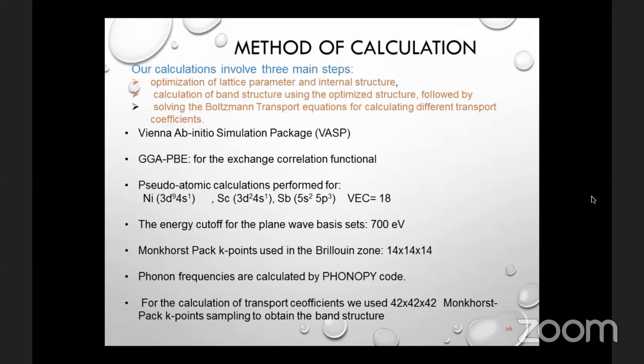But for the band structure calculation, we need more detailed and more sensitive band structure. So we increase the k-point mesh grid, because for the calculation of transport coefficients using Boltzmann transport theory, we need to calculate the velocity as a function of k for different bands. To get an accurate value of electronic velocity, it is necessary to have a dense k-point mesh.